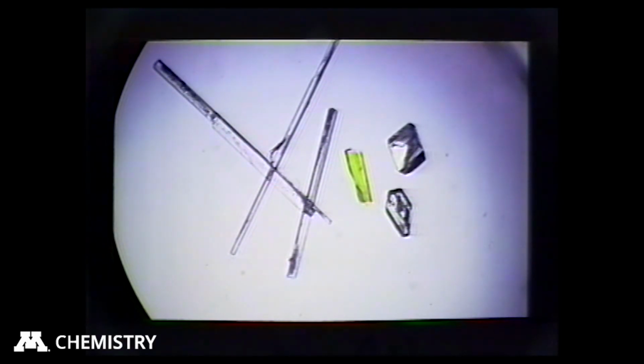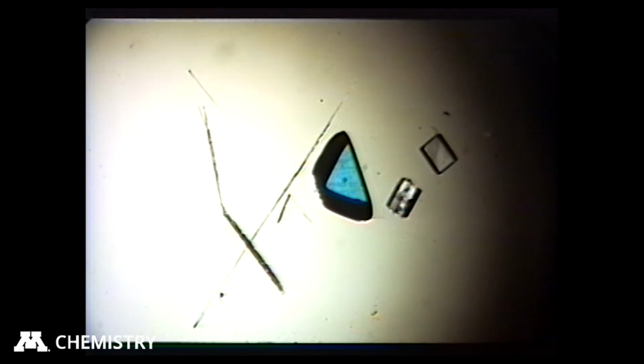Here on the left is para-aminobenzoic acid, and on the right is 4-chloro-3,5-dinitrobenzoic acid, and there's their co-crystal. And I also talked in the first part of this series about the solid-state reaction that occurs in this co-crystal, where you get the nucleophilic aromatic substitution reaction. And now this one is para-aminobenzoic acid again, 3,5-dinitrobenzoic acid again, the nice crystals, and here's their co-crystal pair, and